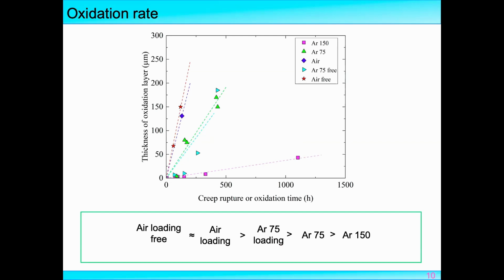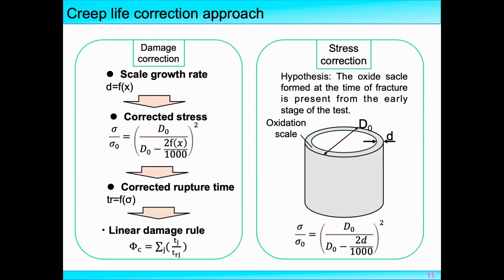So in order to quantitatively analyze the oxidation scale growth rate, we did lots of tests and measured the thickness of the oxidation layer. And here we can see that the oxidation scale growth rate for the air loading condition is the fastest, and the growth rate for Ar 150 is the lowest one.